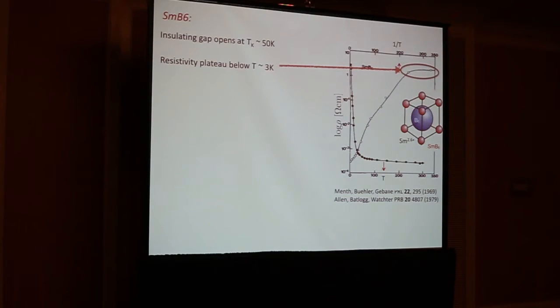And this resistivity plateau was always there, and people tried to understand it in terms of conventional insulating behavior. Was it some kind of mid-gap state produced by impurities? There were immense studies trying to adjust the impurity quality in this gap. This plateau always stayed. And so in the new environment of topology, it raises the natural question: could this be shorting due to the formation of topological surface states?